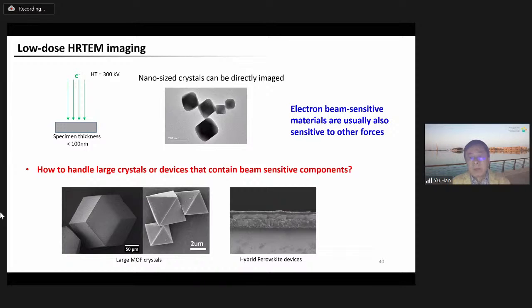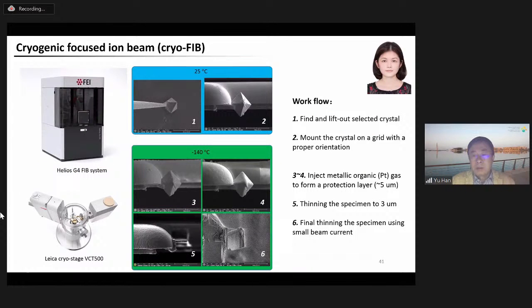Okay? So, I will again make a long story short. I just show you what we have done. So recently we discovered a solution to this challenge. As you know, focused ion beam (FIB) is a common method for preparing TEM specimen, right? And it's widely used in semiconductor industry, FIB to prepare specimen from the chips. And the advantage of FIB is that it allows site-specific and also orientation-specific extraction of the specimen from a bulk crystal or from a device, right?